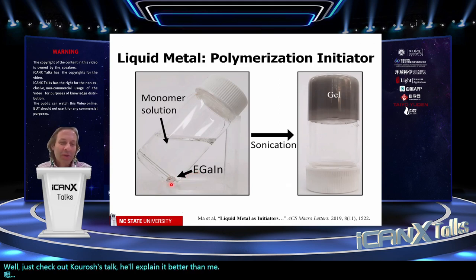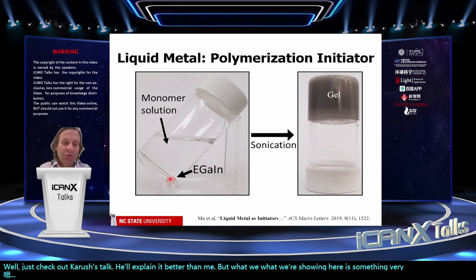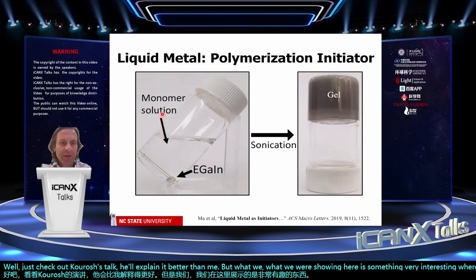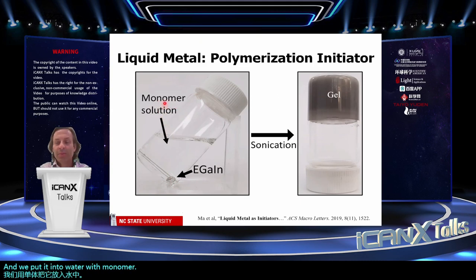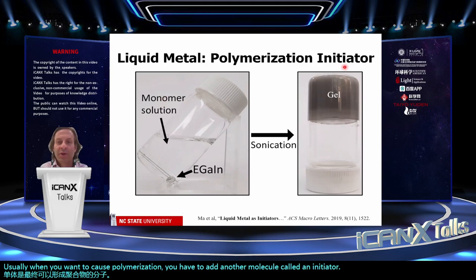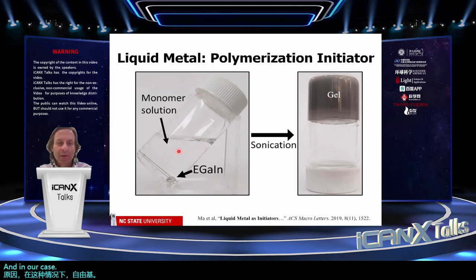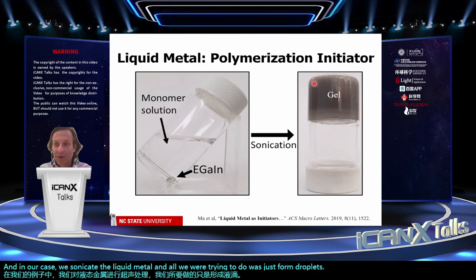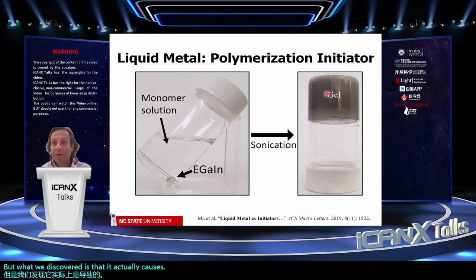But what we were showing here is something very interesting where we take a droplet of liquid metal and we put it into water with monomer. Monomer is the molecules that ultimately can form polymers. Usually when you want to cause polymerization, you have to add another molecule called an initiator. An initiator is a special molecule that causes, in this case, free radicals. In our case, we sonicate the liquid metal, and all we were trying to do was just form droplets. But what we discovered is that it actually causes the monomer to polymerize, and we formed a gel. So when you turn it over, it's no longer liquid. You can see it's now polymerized.